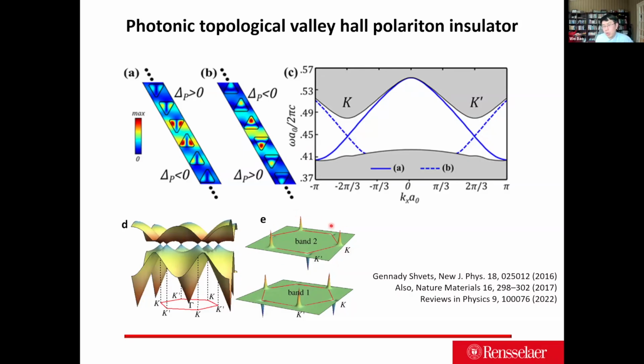If you run the Chern number calculation, you realize this is due to the different, flipped-sign Chern number along the valley. Such a topological valley Hall design, I want to emphasize, is not robust against all kinds of perturbations. It's only robust against perturbations that preserve the C3 symmetry. So compared with the quantum Hall design, which is robust against all kinds of perturbation, this has certain limitations. But the good thing about the valley Hall design is that you can have a much larger band gap opened up, and the fabrication is relatively straightforward as well.